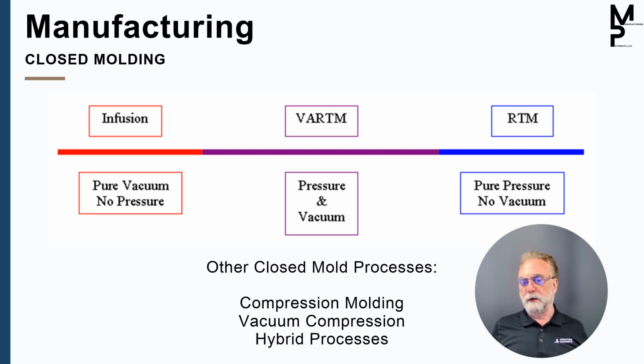It's important to know that a part does not have to live in one state during the whole molding process. Often, especially in VARTM, you will be adjusting the injection pressure and the vacuum level during the production of the part. So at some points you may be closer to infusion in the process, and at other points you may be closer to RTM. You might start out with a very high vacuum and a low pressure, and transition as the part gets full. You need more pressure to push the resin, you might be upping the pressure on the part, transitioning closer to an RTM process.